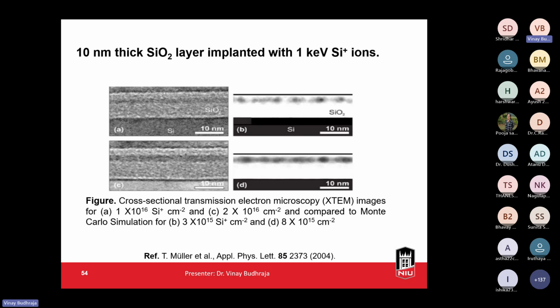In this case, it is showing a 10 nanometer thick SiO2 layer implanted with 1 kilo electron volt silicon plus ions, and the XTEM images show two different doses: one is 1 into 10 power 16, and another is 2 into 10 power 16. And the film growth was pretty uniform from the ion implantation.